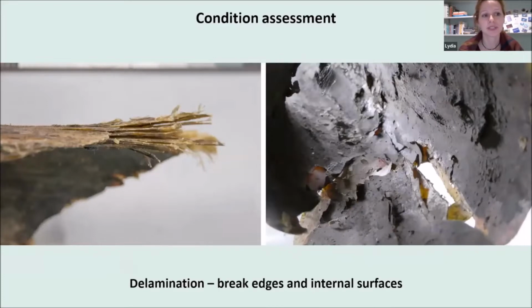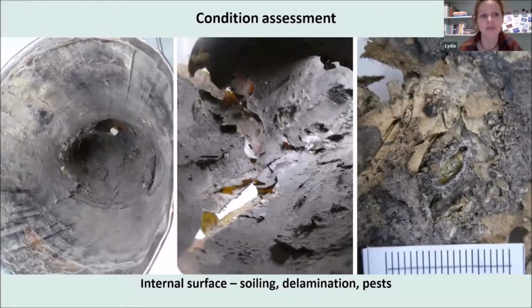The horn material was delaminating into countless paper-thin layers along the break edges and showed some lifting of material on the internal surface as well. Moreover, the inner surface of the horn was heavily soiled, with encrusted layers of dirt, which served as breeding ground for pests. And here you can see, between some paper fragments and dirt, there's like a little larva skin still attached to it. Something really had lived in there.